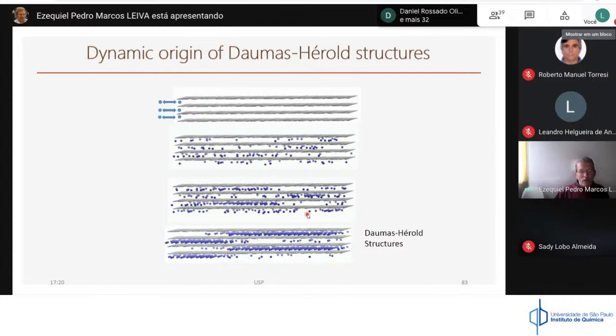The origin of this defective structure is that when you start filling ions into the system, you get a homogeneous distribution. At some point, your system should go to this stage where you have one filled, one empty, one filled, one empty. But the system is not able to do that, because in order to do that, you would have to take away all the atoms and put them inside again. So the origin of this defective structure is a kinetic reason. The system cannot reach a proper equilibrium and tries to do the best it can.